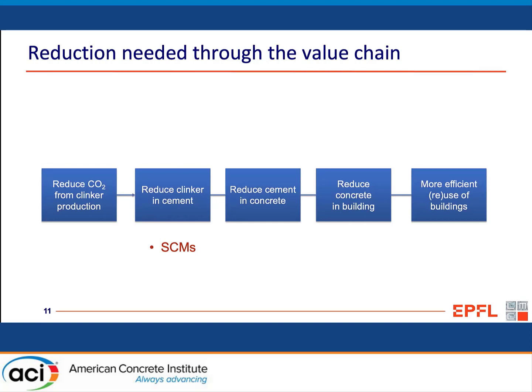I don't think we should stop there, because I think there's a lot more we can do. So we really need to think of this chain. We need to make sure that we produce clinker in the most efficient way. This is largely already done because it's a question of cost. Then we need to reduce the clinker in the cement as far as possible. And we can do this very effectively with SCMs, particularly with calcined clays. We even have formulations now down to 35% clinker, which give very, very good performance.